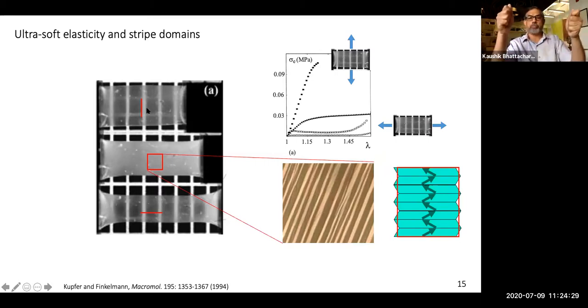And of course, the grips don't allow it. And therefore, what you find is half of it goes one way, the other half goes the other way, creating this fine scale structure, which makes this material cloudy. And then when it's all aligned, it becomes translucent again. And this is the kind of soft behavior that you see.